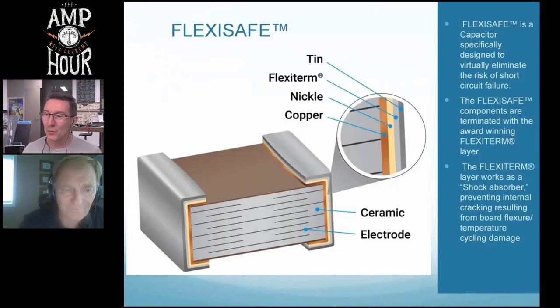Wow, that's incredible. So what are the different technologies for the, you've got FlexiSafe trademark, but I'm sure you do different techniques for flexible end caps. This is what I've talked about in my video. As the board flexes like that, the end terminations can decouple that stress from the ceramic. That's right. You've got different techniques for that? We do. Now it's stabilized to one material system, and it's a great trade secret, but it basically has a conductive epoxy. And that could be very problematic, because if it's not the right conductivity, we increase the ESR. Yeah, you screw up your ESR.